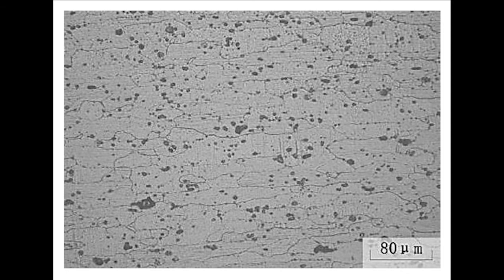In the case of T6511, there are a few different methods, but the graph I have shows heating the material to 535 Celsius for 2 hours. This will cause the alloying elements, mainly magnesium silicide, to be dissolved into the aluminum, strengthening it. After this step, the material is quenched, which involves the rapid cooling of a material in a solution. When quenching is performed on 6061, it traps the magnesium silicide inside, preventing it from precipitating. With quenching, the faster the material cools, the less the alloying element will precipitate.